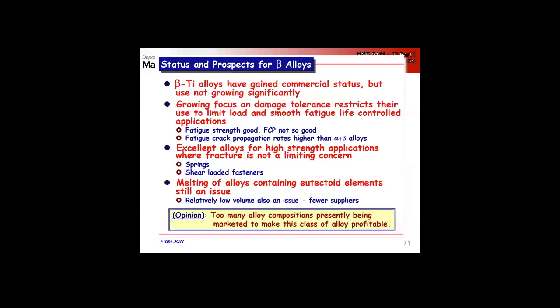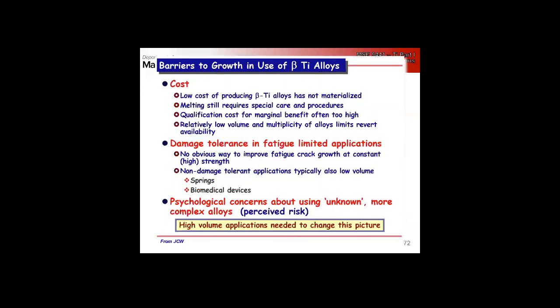Crack propagation rates are a little higher than alpha plus beta alloys. There are good opportunities in things like springs and shear-loaded fasteners. There are still problems with processing eutectoid elements. Cost, this is where your comment comes in. It's more expensive to produce beta titanium alloys in the structure that you want, versus the alpha plus beta alloys. There's a whole ton of alloys listed there. Each has its niche application. So that means it's always being processed in small batches, which drives the cost up.